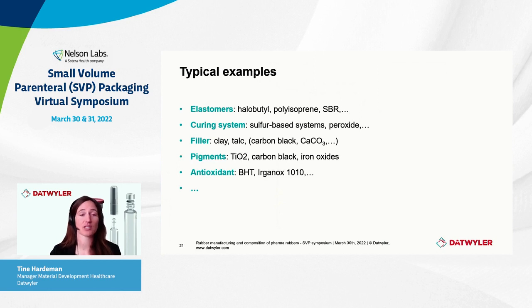Next, we have the pigments. As mentioned, pigments are really preferred over dyes. And then the three most popular pigments are titanium dioxide for white, obviously, carbon black for black, and iron oxides for this rusty red color. And of course, it's possible also there to make combinations. And of course, combining white and black can give you all different shades of gray. And then finally, there's also the antioxidant, which I think many of you know. BHT is, of course, a very, very well-known example, as well as Irganox 1010, but there are also different types of grades possible there.